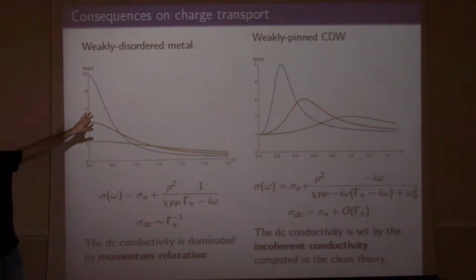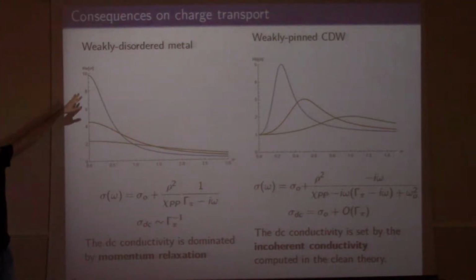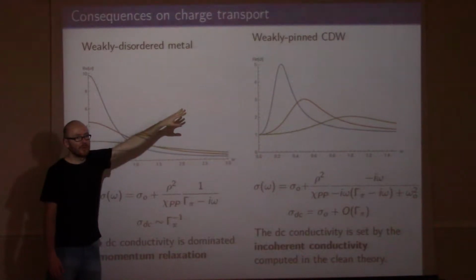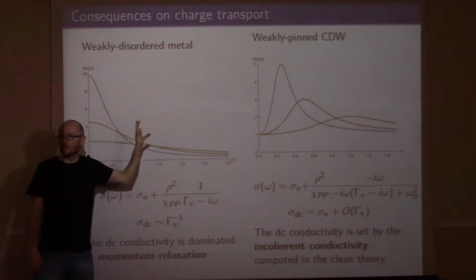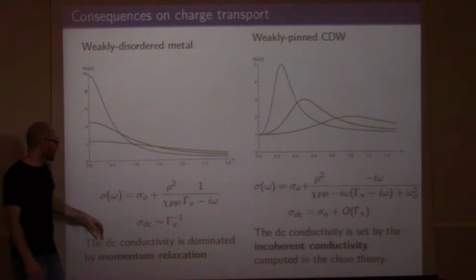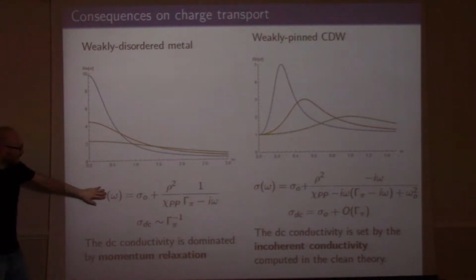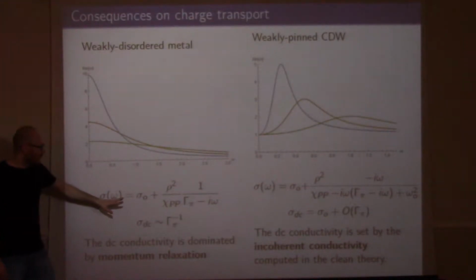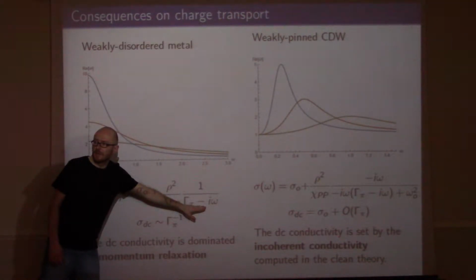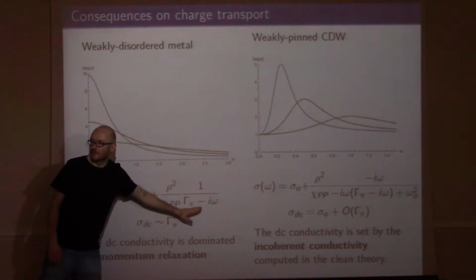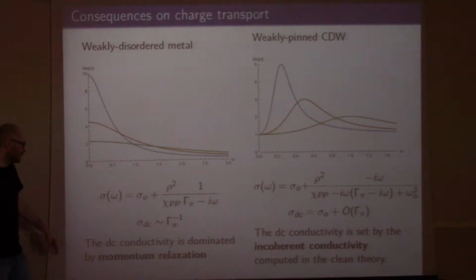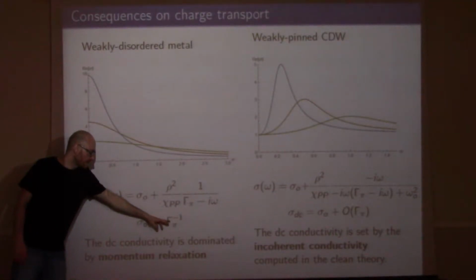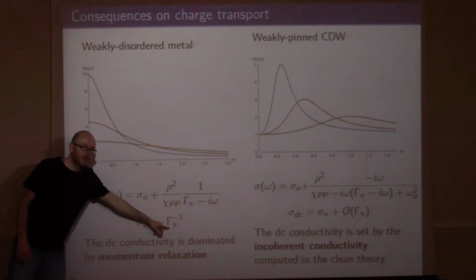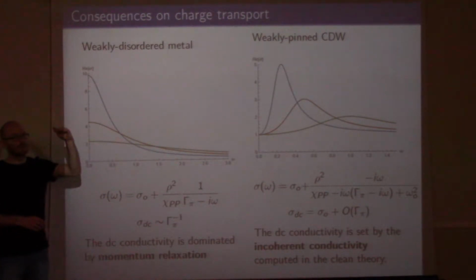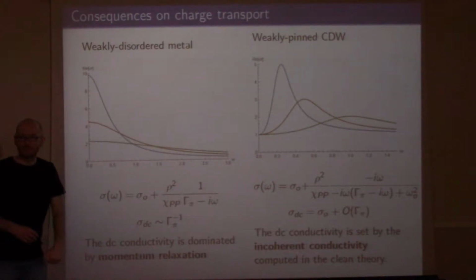So I've tried to put both the weakly disordered metal case and the weakly pinned CDW case, so that you can contrast with what I was telling you the last few days. So you remember that for a weakly coupled metal, this is what the conductivity would look like. Importantly, there would be this pole, purely imaginary, with a lifetime that's given by the momentum relaxation rate. And when you took the DC limit, the DC conductivity would be 1 over the momentum relaxation rate. So if this is a small parameter, then the DC conductivity would be big. So this would be a good conductor.